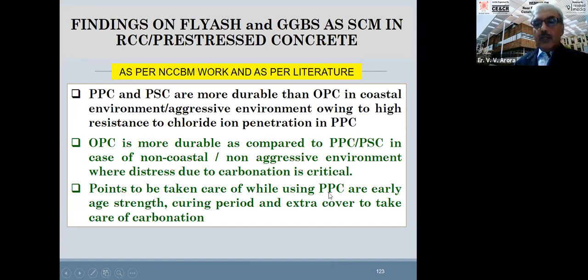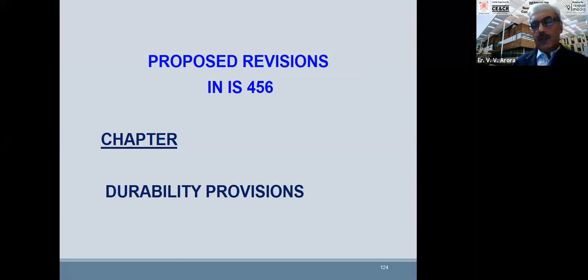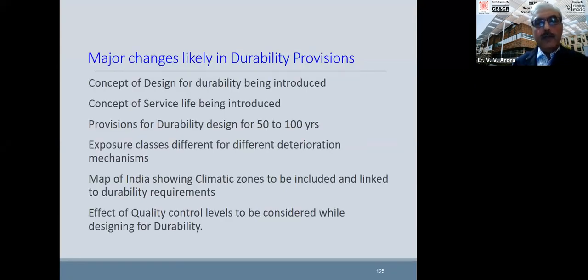So points to be taken care of while using PPC are early age strength, curing period, and extra cover to take care of carbonation. If you use a little higher grade or a little more cover, then the deficiency is covered up. So in the new IS 456, you will have complete details on those things: when you are using this kind of cement, what cover will be required, what grade of concrete will be required, and things like that. And then you can test the carbonation coefficient also. We give carbonation resistance coefficients based on the water cement ratio and type of cement also. That will be for simpler usage. And you will be able to test it also in the laboratory.